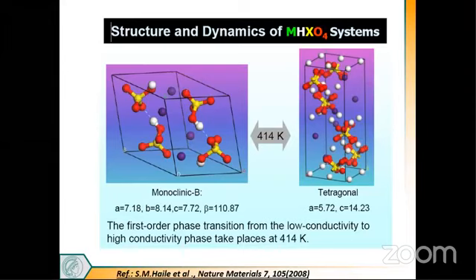And being a crystallographer by training, I would like to explain it better from a crystallographic point of view. So, for example, in this particular molecule, which is rubidium hydrogen sulfate based, RbHSO4, the temperature is 414 Kelvin. Below that temperature, we have a monoclinic phase, and above this temperature, we have a tetragonal phase. So 414 K is the triggering temperature where the rotation mechanism kicks off, and with the inception of rotation, as the rotor molecules get activated, we encounter a phase transition.